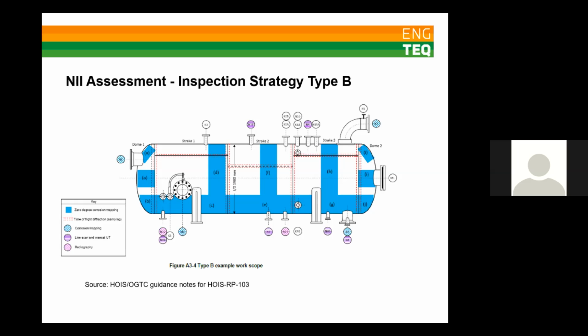So the results for this inspection may then be used to estimate the worst case flaw for the remaining area by statistical analysis, provided that the areas inspected are representative of the areas that haven't been inspected. So note again that the nozzle coverage is similar to the type A example. So there's more than 25% coverage at the nozzles. So again, you're looking at the main process nozzles individually. So that's the inlets and outlets, for example, and then a sample of the minor nozzles.